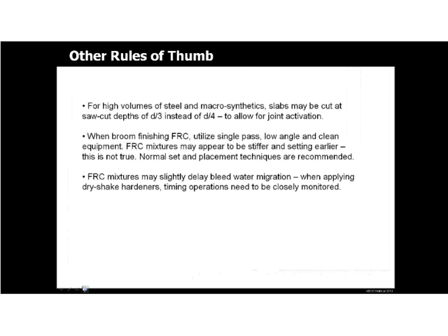Some of the other items that I wanted to cover with regards to the use of fibers, and although there are some theories on what is correct and what is incorrect, some of the things you may need to be aware of when using higher volumes of steel and macrosynthetics is when you are saw cutting the joints, you may need to cut slightly deeper to allow for those joints to activate. If you can imagine, a saw cut joint with fibers across it, especially for high volume, is basically like stitching concrete together. Extremely high volumes of fiber may actually cause a crack where fibers are present to be stronger than the surrounding concrete.